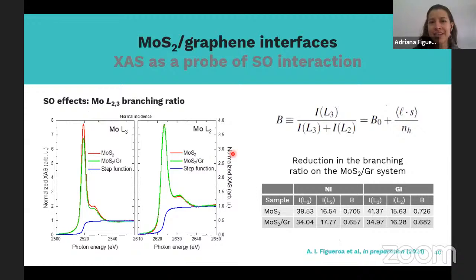In terms of the branching ratio, which is the one we were interested in, we analyzed that for the molybdenum L2,3 edges. We extract the information by application of this sum rule for molybdenum. We see that there is a reduction in the branching ratio for the MoS2 graphene system as compared with the bare MoS2 without the graphene. That is related to a change in the spin-orbit coupling in these stacks. So this is the main result in that case.